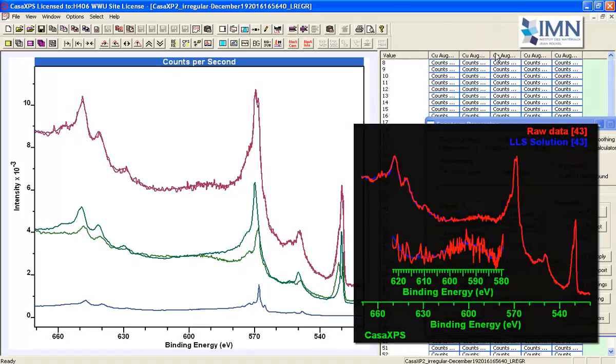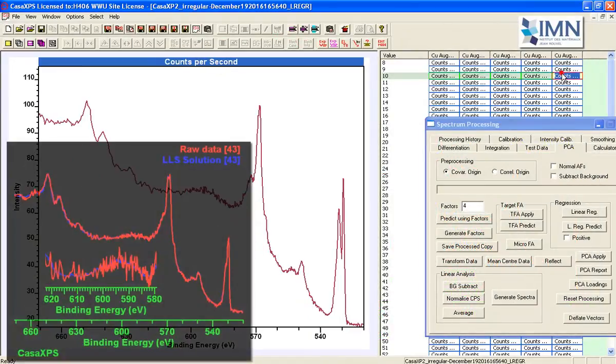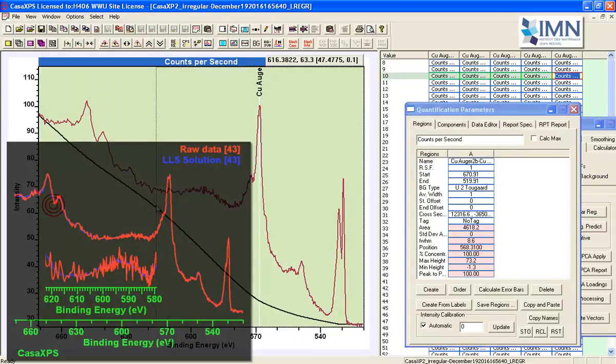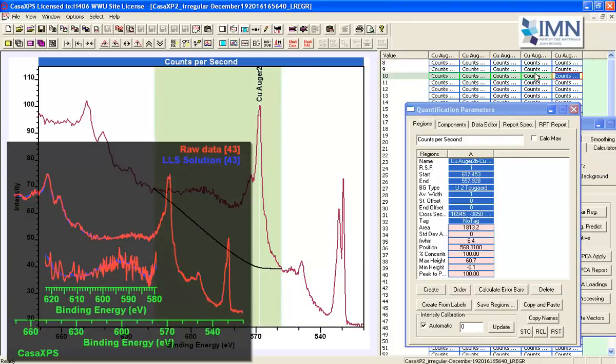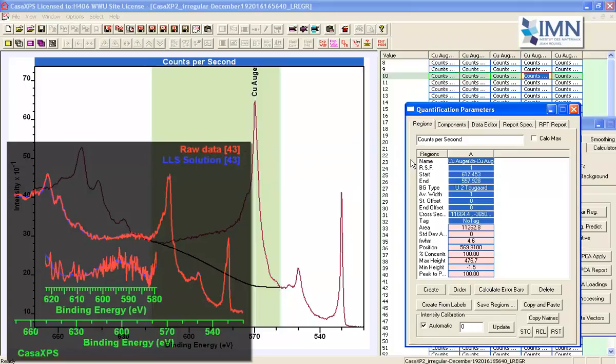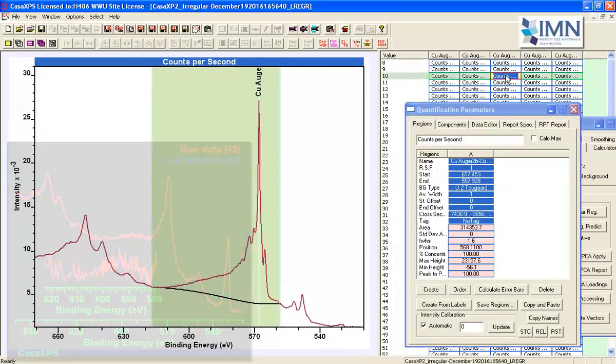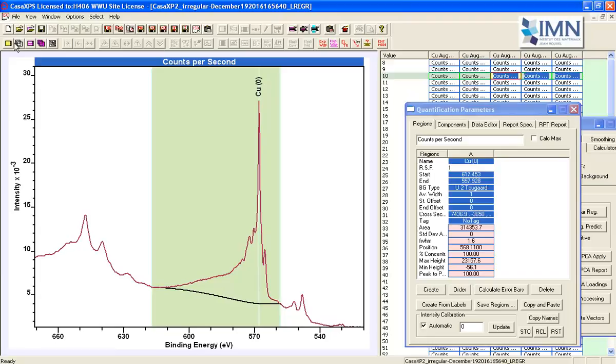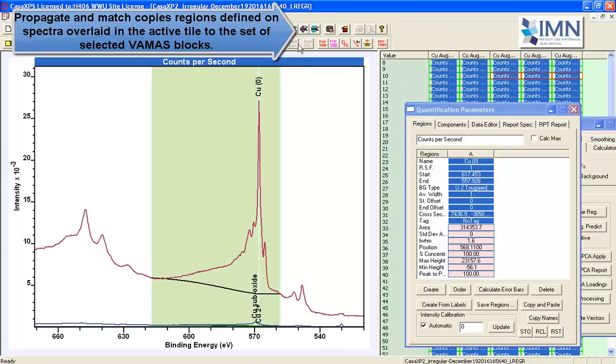We've reproduced the data very nicely — it's much smoother than the raw data because of the PCA calculation. If we hadn't done PCA, the basis functions would have been much noisier; but because we had such a large data set we were able to remove noise, having invested significant acquisition time. We then add regions for the Auger peaks — the primary Auger peaks, though there are many peaks beneath these complex structures that you'd never want to peak-fit. We can put regions on to estimate the intensity associated with different Auger structures, create a profile, and name the different regions so that the quantification table traces have appropriate names.